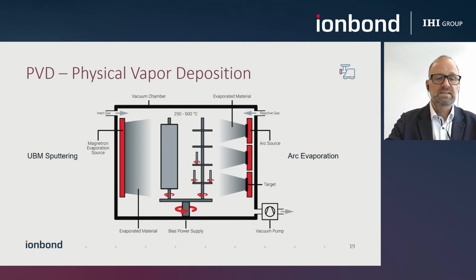And next, we have these targets. This is how it is called. The targets are made out of solid material, like, for instance, titanium. Those are marked in this graphic with the red bars, one on the left, three on the right. And by means of an electric arc or by sputtering, we can evaporate, or we can remove parts out of the surface of the targets. And these electrically charged particles, titanium particles in this case, are then accelerated by an electric field to the surface of the goods to be coated. Once they arrive on the surface, they adhere to the surface and get part of the surface and form the coating.